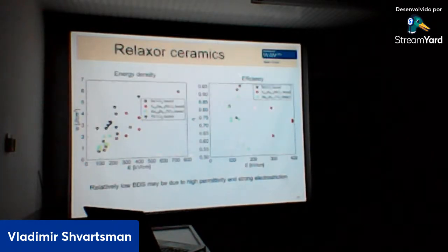So just a comparison between different materials taken from literature based on the different ferroelectric systems. What we can say about relaxor ceramics is that they usually have good energy density, and in principle efficiency is also okay, but typically these relaxor ceramics have large dielectric permittivity, and therefore they have low breakdown strengths.